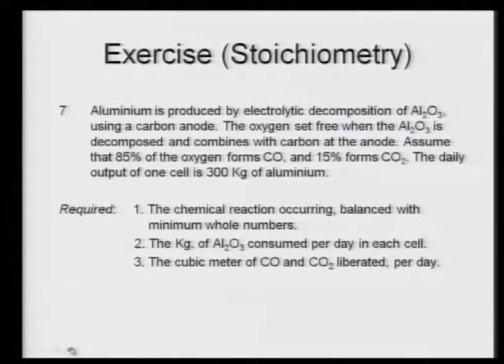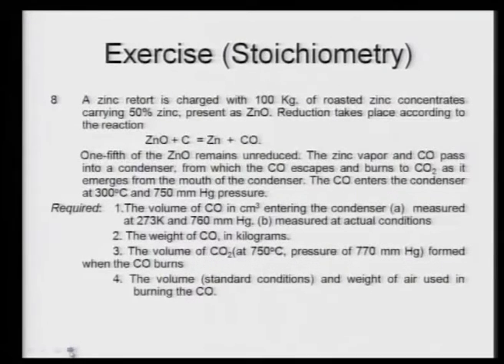So, aluminum is produced by electrolytic decomposition of Al2O3 using a carbon anode. The oxygen set free when the Al2O3 is decomposed combines with carbon at the anode. Assume that 85% of the oxygen forms CO and 15% forms CO2, then you have to find out the chemical reaction, kilograms of Al2O3 and cubic meters of gas when 300 kilograms of aluminum is produced by one cell. So, that is problem number 7. The problem number 8 is typically the reduction of zinc oxide by carbon.